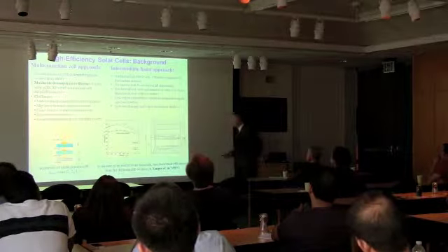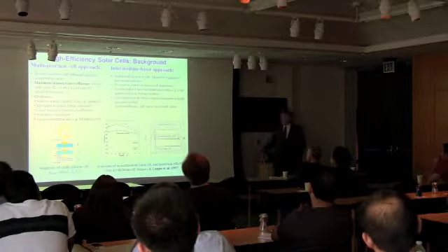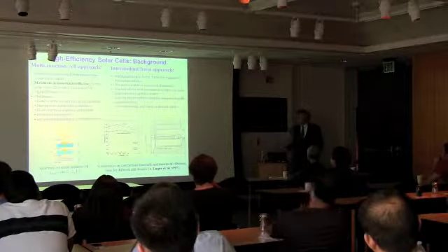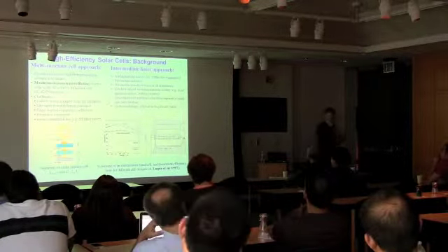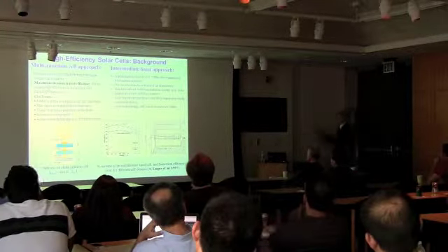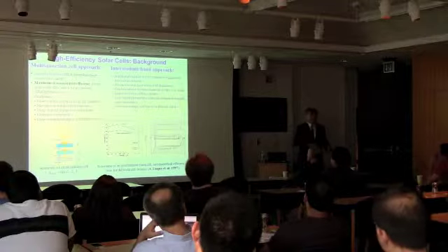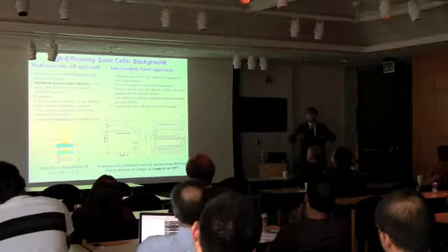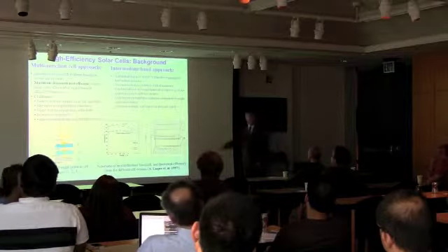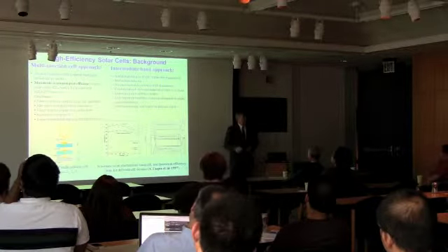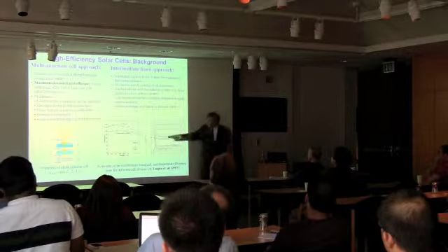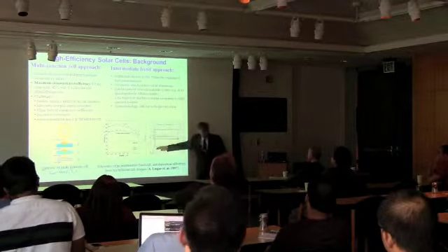They say, okay, we have a certain material, and inside of this material we will put something that will create a so-called intermediate band. To create the intermediate band, the easiest way, and there was much discussion, is to put in quantum dots. So you put quantum dots inside, you create the so-called intermediate band. Now, by changing the dot material and so on, I can move these from here to there.